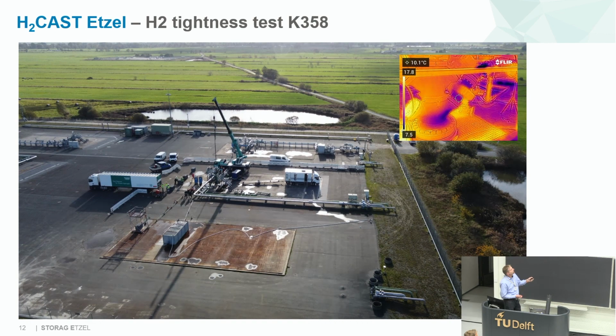So we injected the hydrogen. It took only about 3 hours. It was much easier than we expected before. And then the whole test took about 3 months, with several measurements from time to time to calculate the amount of hydrogen which is still in the well, to approve the tightness.